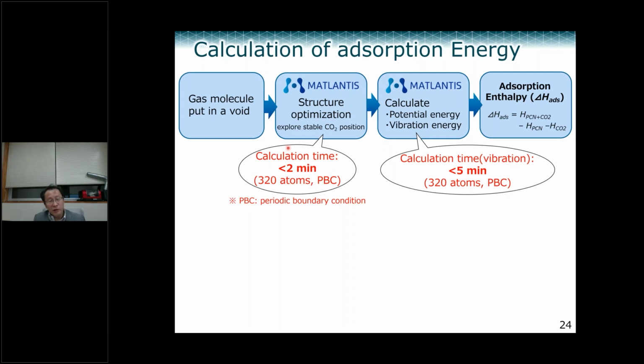Of course, if you use a supercomputer, it's much faster. However, surprisingly, you can calculate this kind of structure. This structure has even 320 atoms, and we applied a periodic boundary condition. This is quite an impressive result for us. Then we calculated the potential energy and the vibrational energy as well. In this case, it takes less than 5 minutes. Then we calculated the adsorption energy.